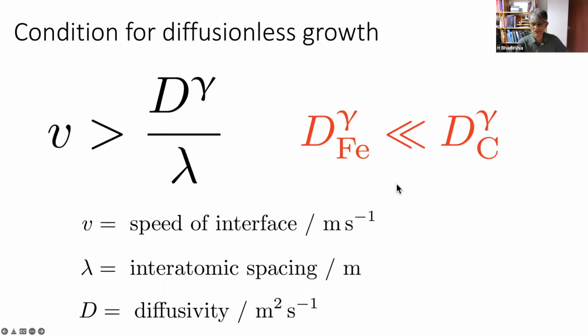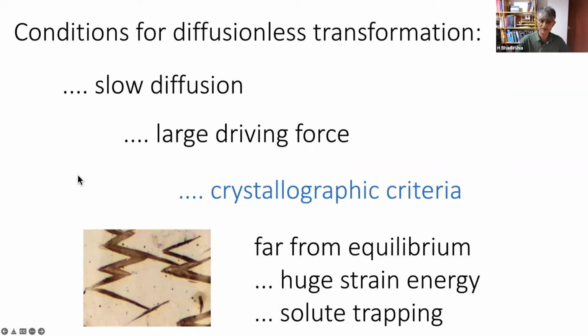And of course, the complication is that we have two different species here, the large atoms and the small atoms. So this equation could be satisfied for the large atoms, but not necessarily for the small atoms, as I pointed out earlier. But of course, what determines the velocity of the interface? Well, it's the free energy difference between the parent and product phase. So to get a diffusionless transformation, we not only need slow diffusion, but also a large driving force which wants to push the interface at a high velocity. And there are particular crystallographic criteria which I won't go into today, because those also need to be satisfied to get an interface which is capable of moving fast.